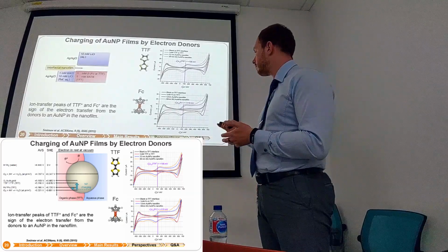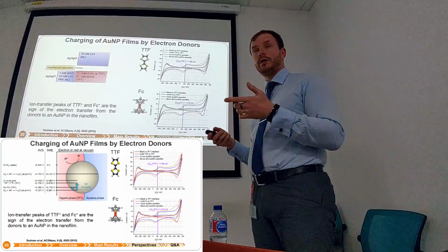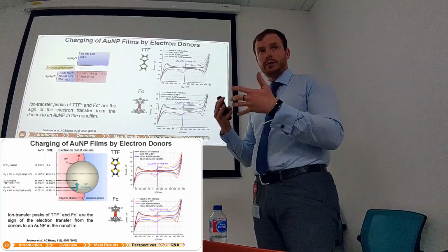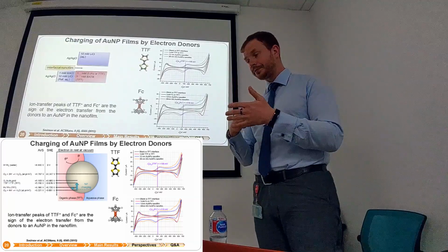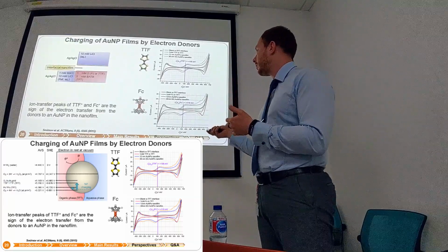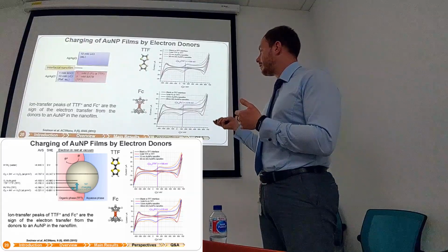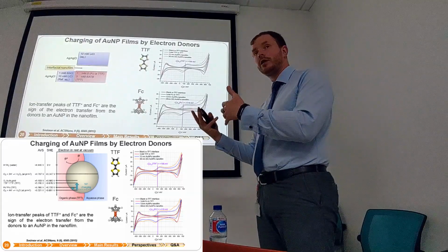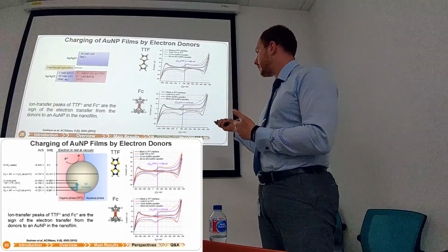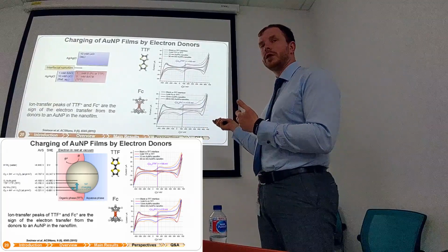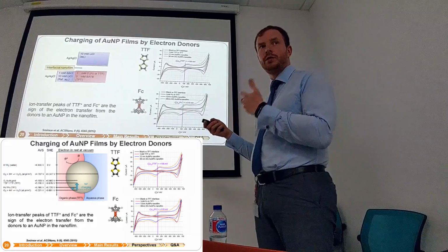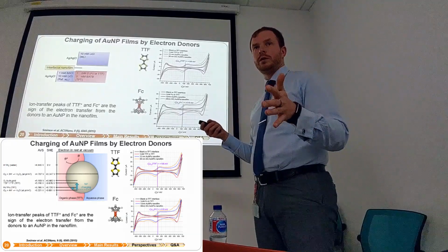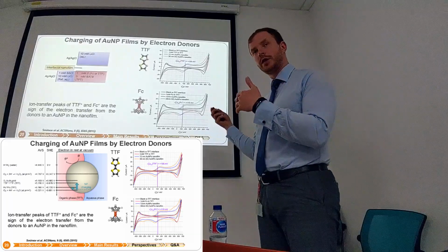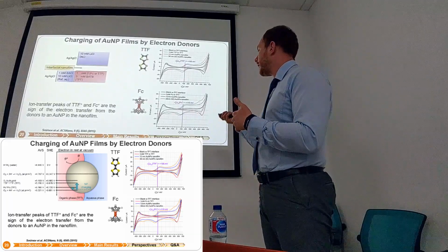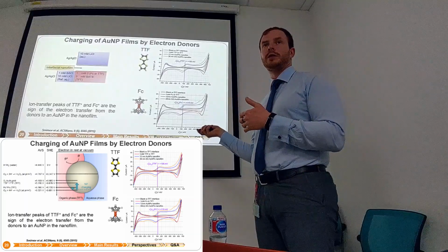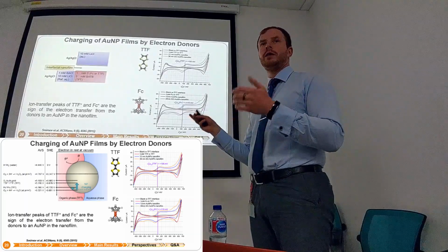So we know that ferrocene is not sticking to the surface of gold nanoparticles. We know that ferrocene is just giving electrons or taking electrons. And in principle, if you leave the system for a long time like this, ferrocene diffuses to the bulk of the organic phase or water phase, because it's charged, it can cross the interface. And this peak disappears after half a day or maybe a day.